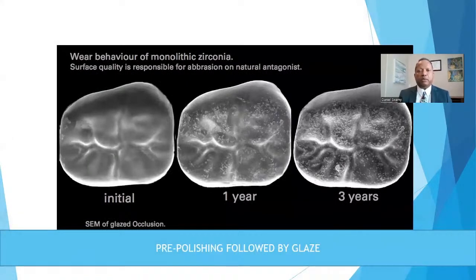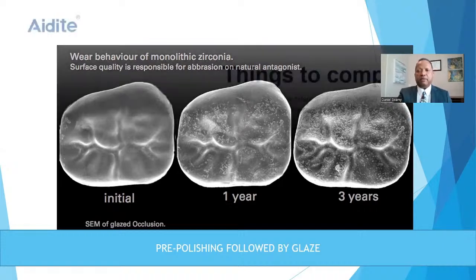So it's imperative that you pre-polish the surface prior to glazing, and then you'll find in this picture that the initial, the 1 year and the 3 year shows how a pre-polished crown wears. So it's very good to pre-polish it, because after 2.5 years, the feldspathic glaze actually wears out, at approximately 6 microns a year. So if you're putting 2 layers of glaze on this, it will wear out in 2.5 years. So what happens is, if you have a very nice polished understructure, the occlusal surface is going to wear like enamel once the glaze has deteriorated.